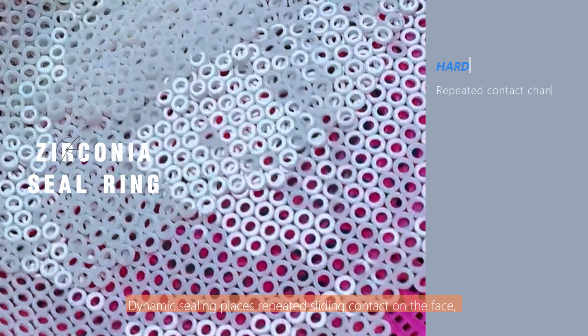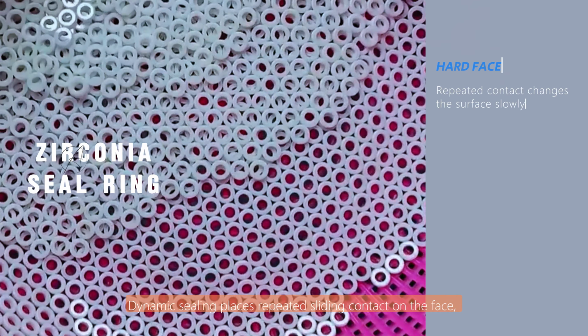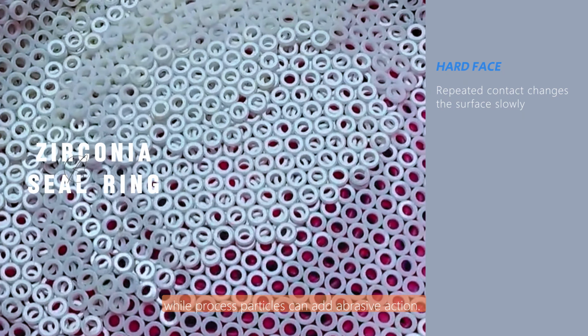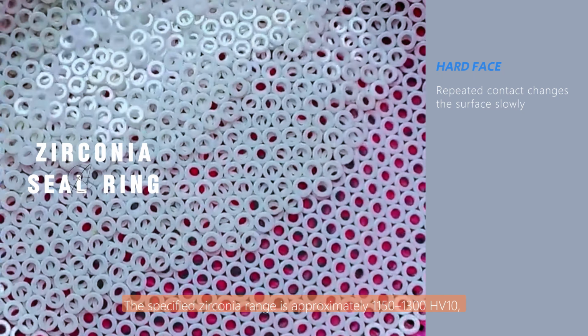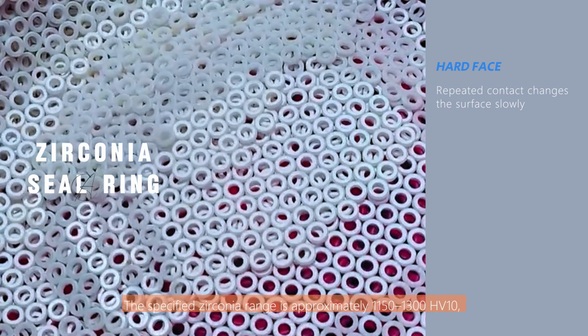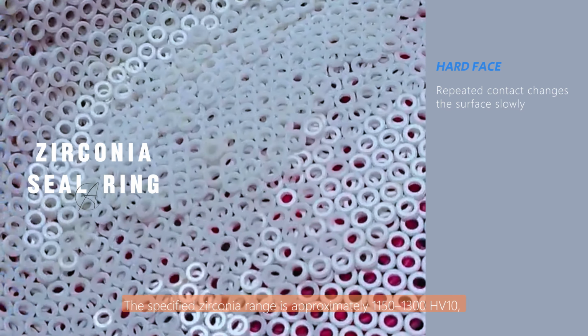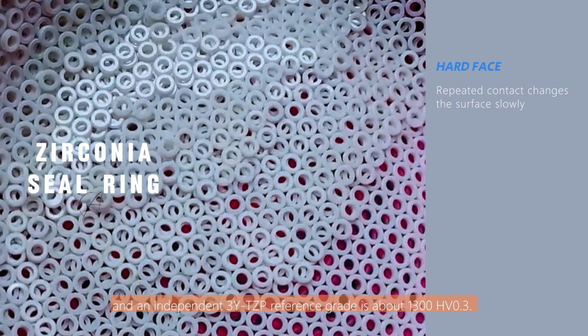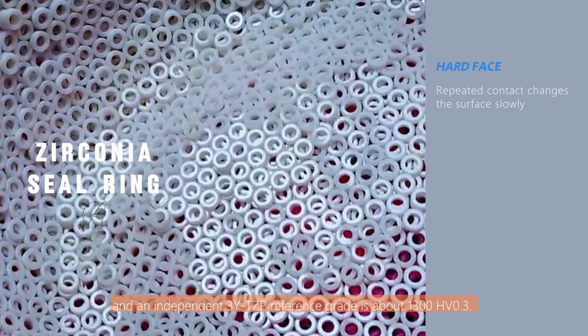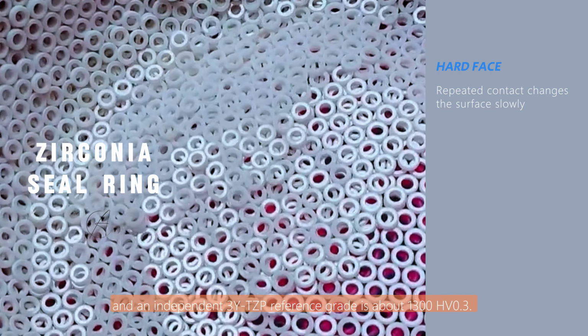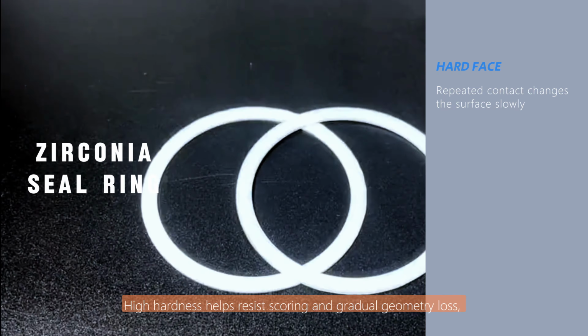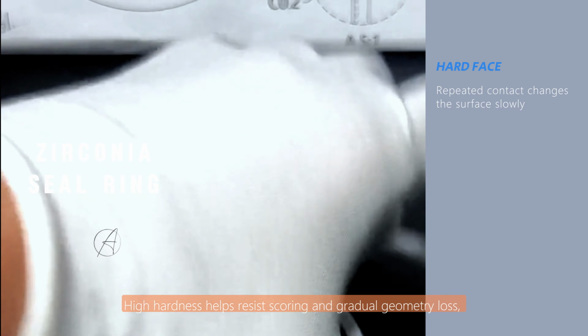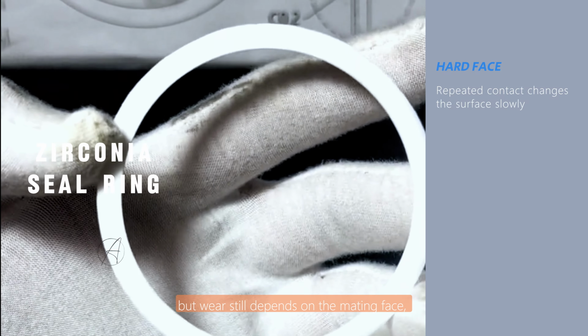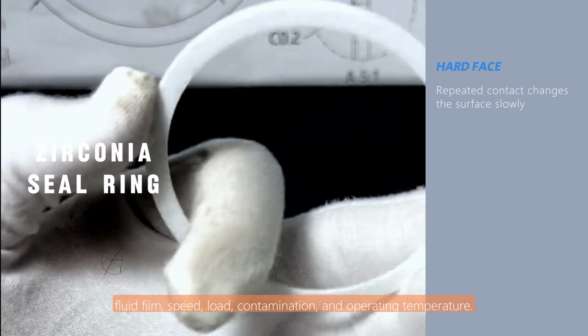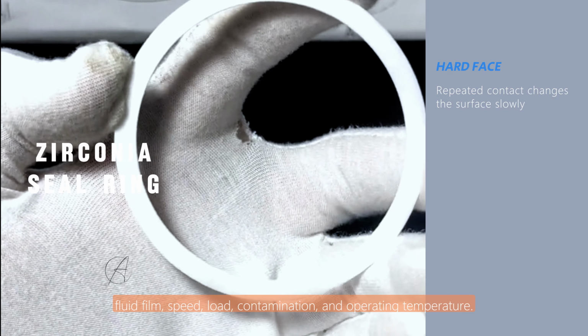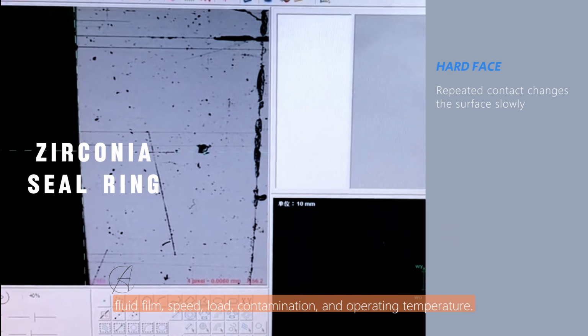Dynamic sealing places repeated sliding contact on the face, while process particles can add abrasive action. The specified zirconia range is approximately 1150 to 1300 HV10, and an independent 3 Y-TZP reference grade is about 1300 HV 0.3. High hardness helps resist scoring and gradual geometry loss, but wear still depends on the mating face, fluid film, speed, load, contamination, and operating temperature.